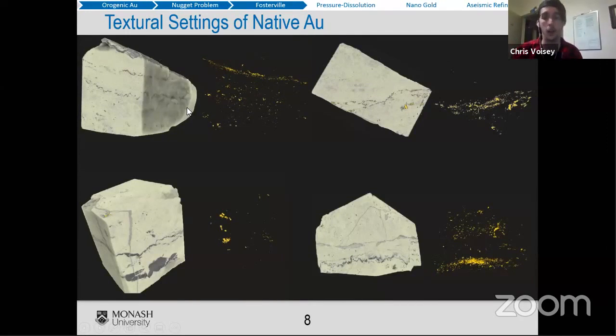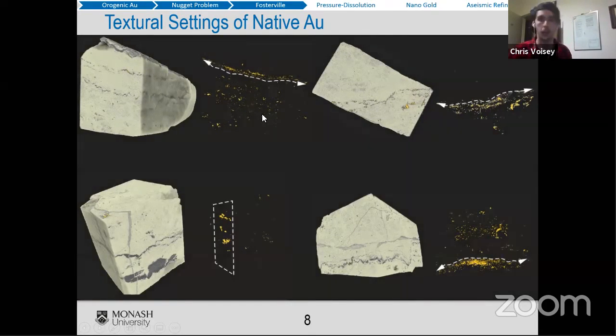And what I've done here, I apologize for showing you a 3D image on a 2D screen, but I basically pulled the gold content out of this sample and put it next to it. So this gold here lives inside this sample, and I've shifted it out so you can see it. And when I first looked at it, this is where most of the gold looks to be concentrated in the samples. You have these sort of planes of gold with some sprinkled throughout, and they correlate with these dark squiggly lines. This one here, a lot of the gold looks like it's in a fracture, which is perpendicular to the squiggly line. And to me, it just drove me crazy.